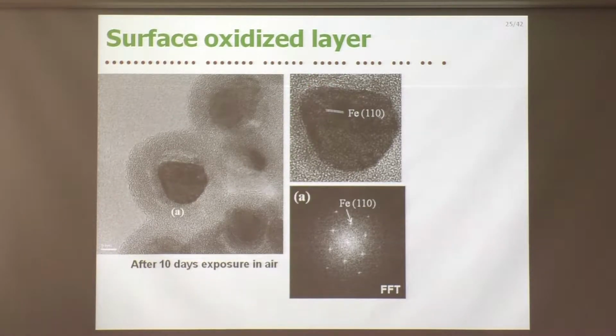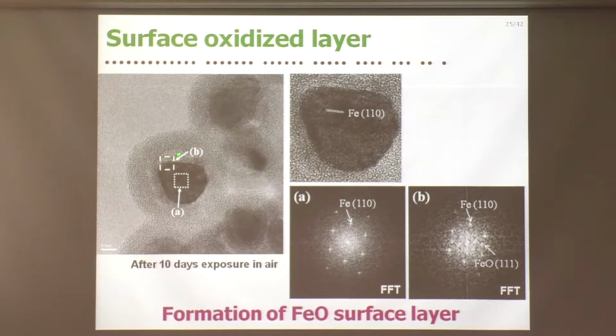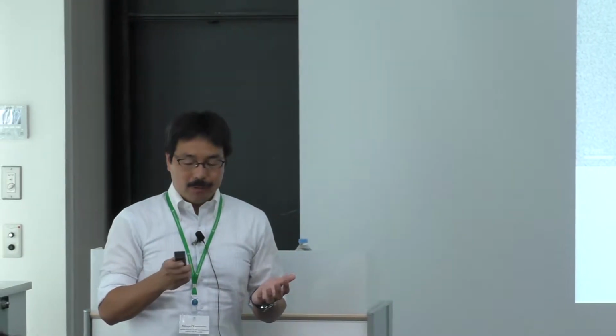The Fourier transform image of the inside of the core is shown here. As you can see, this FFT image consists of only the spot from the 110 lattice of the iron. However, an FFT image from the surface areas of the nanoparticles shows, of course, the spot from the 110 lattice of alpha iron, but also a spot from the 111 lattice of the FeO oxide phase. So we don't know the full details about the oxidized layer, but we can say at least that the surface oxidized layer contains the FeO phase.